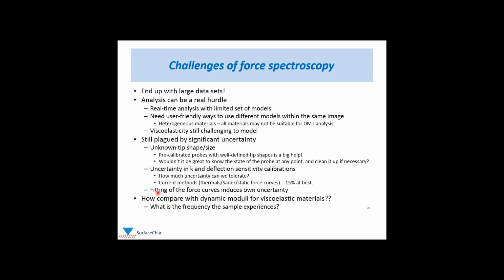And then finally, there are other elements of fitting of force curves, in terms of how you fit the baseline and algorithms of how you fit the adhesion, that actually introduce their own uncertainty on about a 10 to 15% level. And then finally, for force curves, for those that are dealing with viscoelastic materials, be very careful when you're comparing with the dynamic moduli, because we have this question: what is the frequency that the sample is experiencing in our force curves?